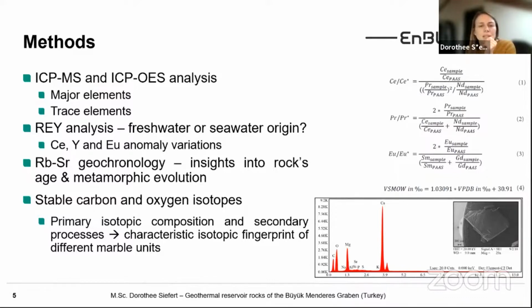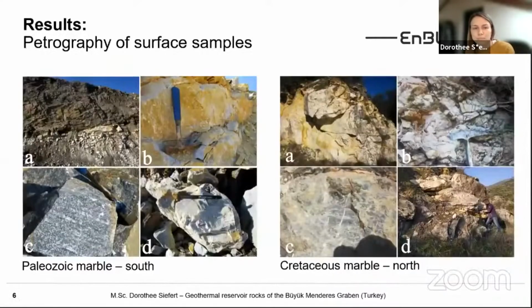And to potentially detect the ages of the marbles, we tried to select impure marble samples with a significant amount of muscovitic white mica and/or biotite, and also the strontium isotopic composition of pure marble samples was measured. And this was done to determine the age of marble deposition from the seawater, and the measurements were done using also a mass spectrometer. So to quickly go over the petrographical